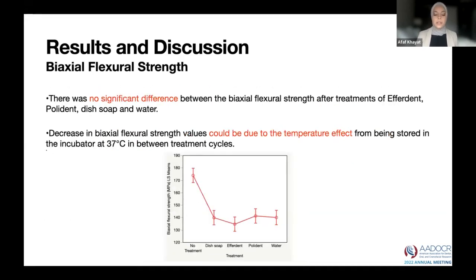For biaxial flexural strength, there was no significant difference between the biaxial flexural strength after treatments of Efferdent, Polident, dish soap, and water. Decrease in biaxial flexural strength values could be due to the temperature effect from being stored in the incubator at 37 degrees Celsius in between treatment cycles.